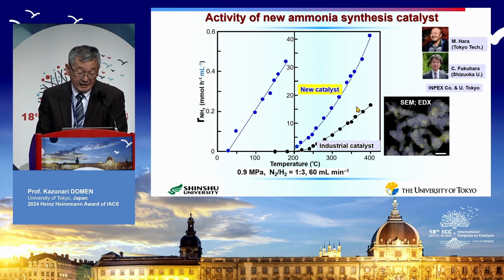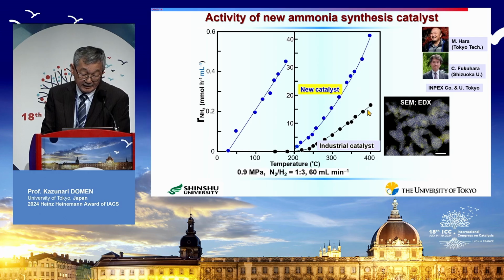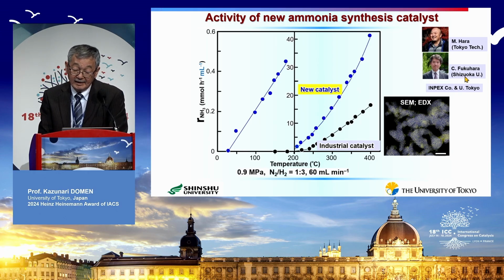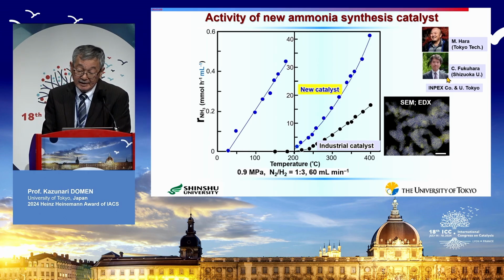Here I show the activity of ammonia formation per unit volume as a function of temperature at relatively mild reaction conditions. This catalyst is a new catalyst developed by Professor Hara at Tokyo Tech. And this industrial catalyst is a comparison, a Haber-Bosch type catalyst. And Professor Fukuhara is an expert on the structure of the catalyst. And it is suitable for our purpose, and also it can avoid the pressure drop in a reactor.